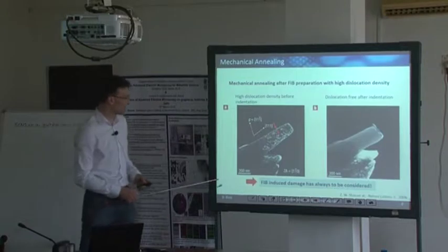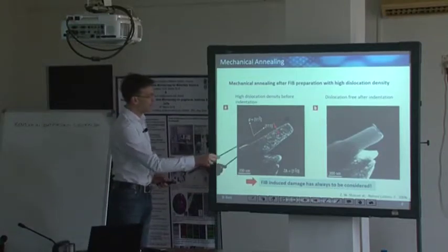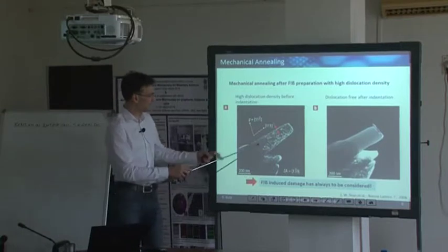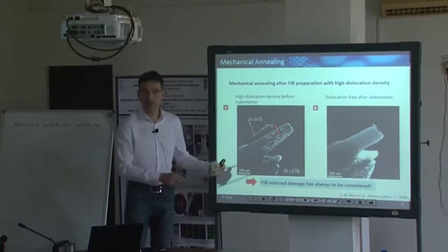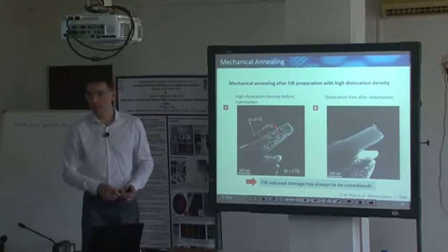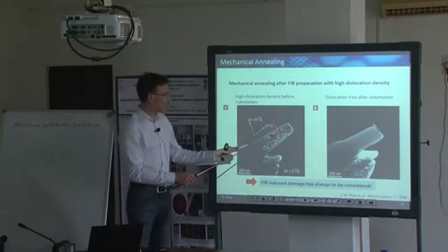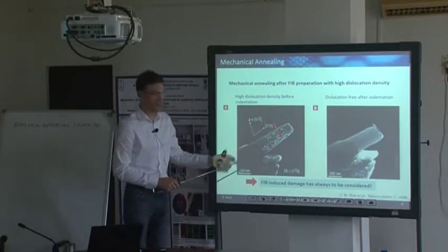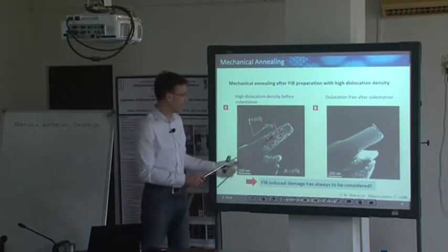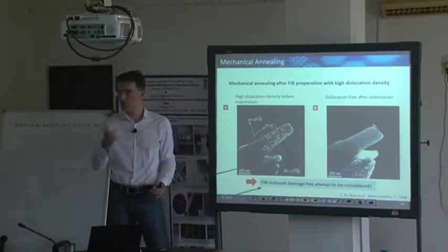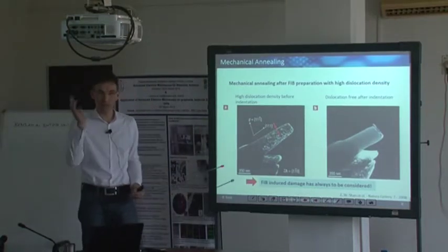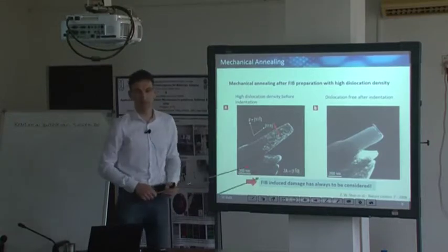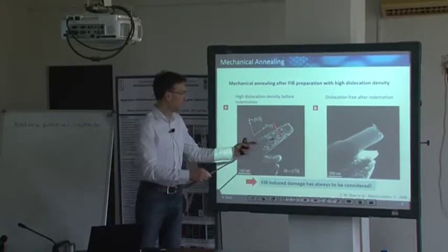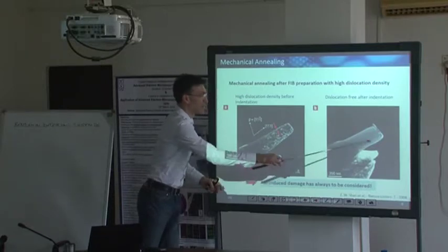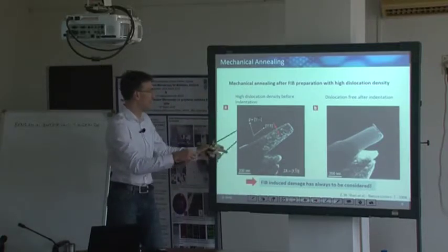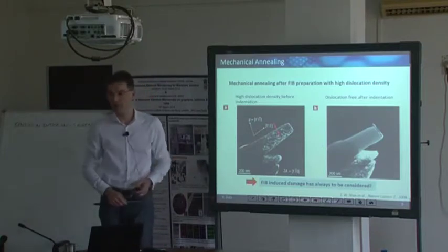This, for instance, is the cross-section of such a metal pillar in the transmission electron microscope. And here you see a very high density of dislocations simply due to the preparation using the ion milling procedure. After mechanical testing, and this is a very small structure, all those dislocations are gone because you have a huge surface area available, and they just moved out to the outer surfaces and disappeared. So this is probably how the material would have been. This is just some artifacts generated by the focused ion beam.